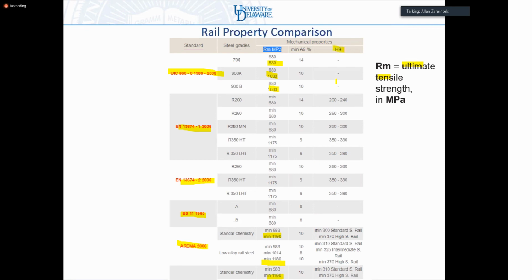Here's the hardness. HB is Brinell hardness. Sometimes it's called BHN, sometimes it's called HB. So you can see the EN standards, the UIC standards aren't listed here, but they're similar to the EN standards. They're between 200 and 300 for the standards, and then up to about 390 for the premiums. The AREMA standards are about 310 for the standard, up to about 370 plus, up to 400 for the premium.